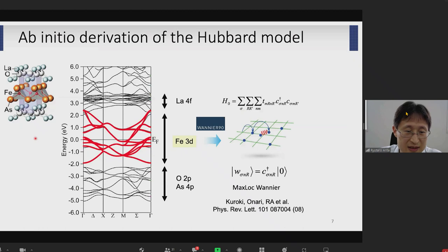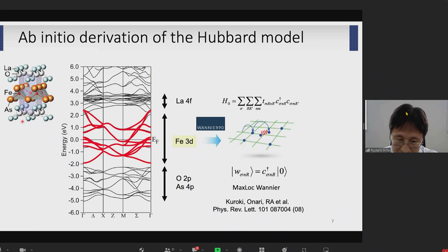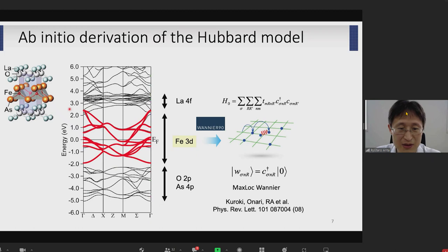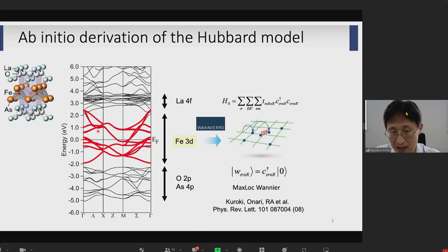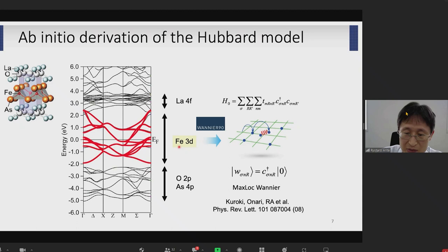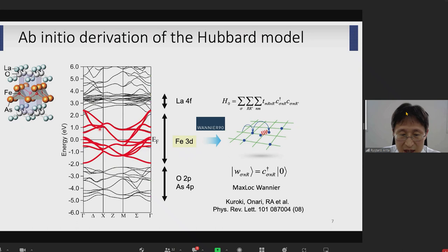When we discuss physical properties — including the mechanism of superconductivity in iron-based superconductors — we need a realistic and accurate low-energy microscopic model. This is the electronic structure of lanthanum iron oxyarsenide. If we look at the band structure, around the Fermi level we have 10 bands originating from the iron 3D orbitals. The unit cell of this compound has two iron atoms, each with five d orbitals — so in total we have 10 bands. Below these iron 3D bands, there are oxygen 2P bands or arsenic 4P bands. Above the iron 3D bands are the lanthanum 4f and lanthanum 5d bands.